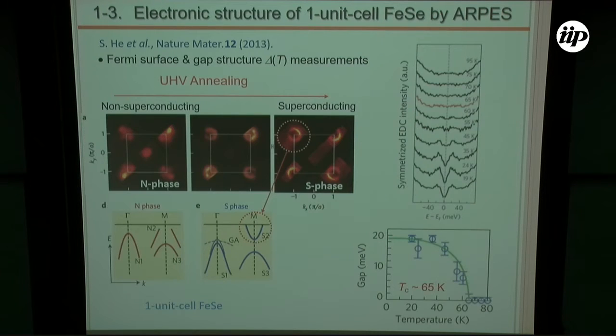the bulk values. Just after this discovery, the electronic structure of the one-unit-cell film was also investigated by ARPES measurement. This picture shows the comparison of the Fermi surface of the non-superconducting and superconducting samples, controlled by UHV annealing. The most striking feature of this superconducting sample is the disappearance of the hole pocket at the zone center and the appearance of the electron Fermi surface at the zone corners. Okay, so this means that electron doping is the most important in these systems. And they also investigated the gap structure using this ARPES measurement. At low temperature, the gap size is almost the same as that of STM, and the gap closing temperature is almost 65 Kelvin, which again is higher than the transport data.